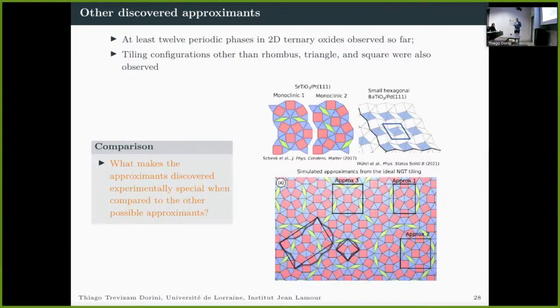So we would like to just try to analyze this question by selecting a few other approximate phases that we can find in the literature. 2 monoclinic phases, 1 small hexagonal phase. This phase is on another system, but for the comparison sake, we have also used this phase for the same strontium titanate over platinum 111. And we have selected manually 3 approximate phases to compare with these other approximants. As you can see, the approximate 1, approximate 2, and approximate 3.